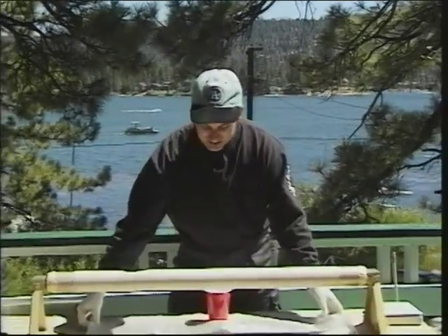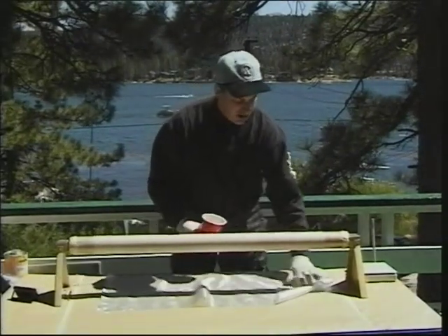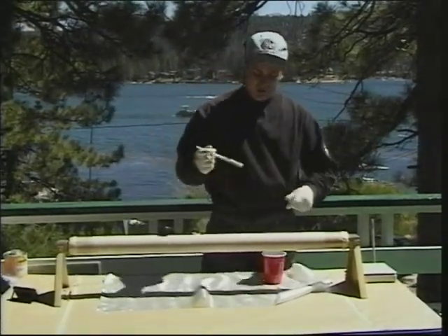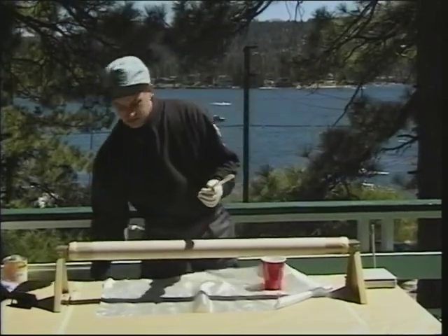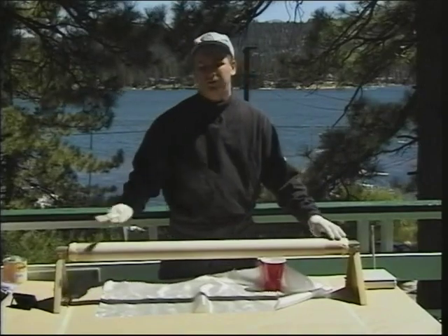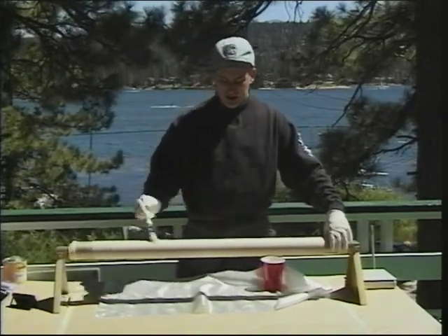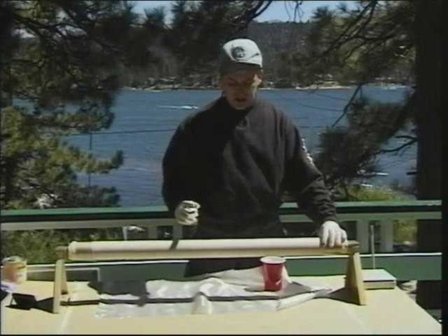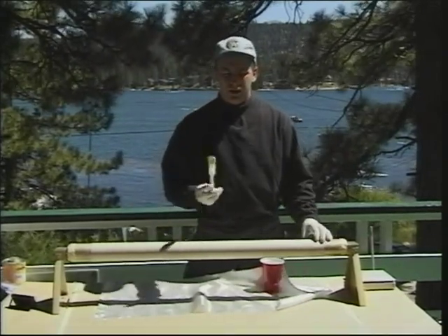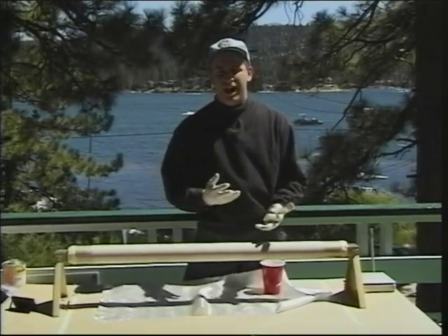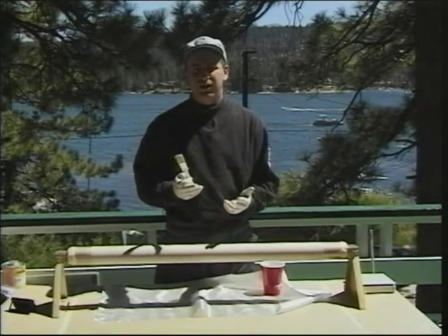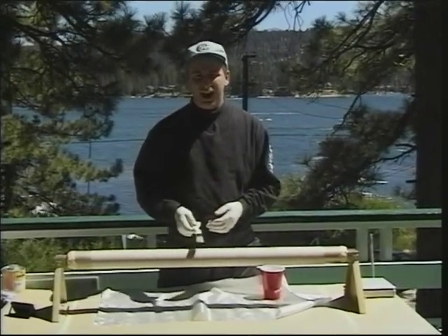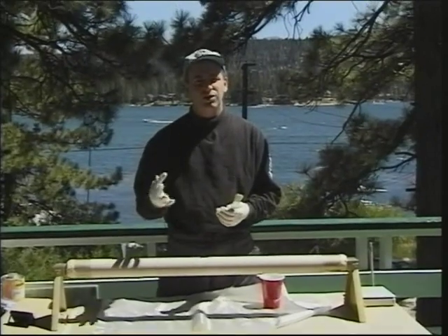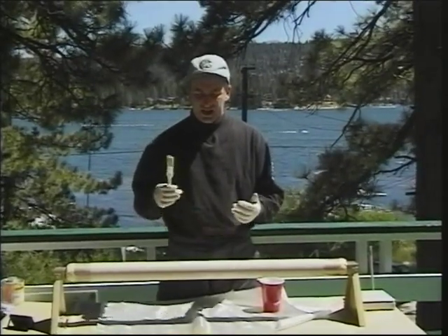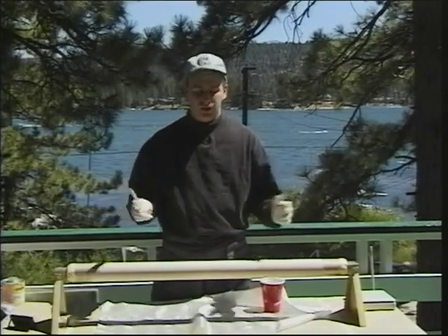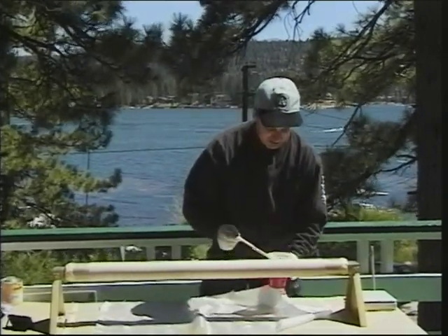So now we've got our resin mixed, we've got our cloth ready, and we're going to start by just using a little inexpensive resin brush to apply some resin to the tube. And I'm just going to basically paint half of this tube around its circumference just to adhere the cloth to it. Now remember, the whole point of doing this is to keep your resin and your cloth ratio as close to 50% as possible. The way you can do that with glass is to apply resin until it just goes clear in appearance, and you don't want a complete glossy sheen over the whole thing, but we'll see that as we get going in this process.